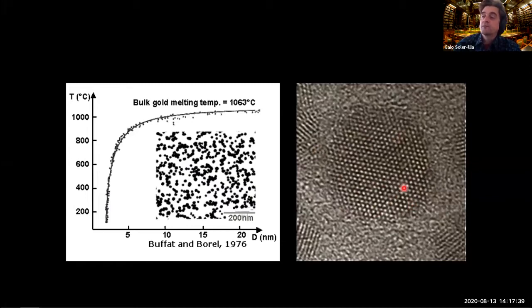So you can record the melting temperature as a function of the size of this particle, and you obtain this logarithmic dependence. What is this telling you? This is telling you that gold's melting point is indeed dependent on the size of the particles. Why is this so? Because a great fraction of atoms are on the surface, and the presence of atoms on the surface destabilizes the particle. The smaller the particle, the less stable it is, the easier it is to melt.